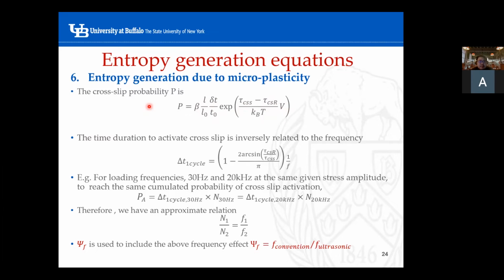So this is a probability, the cross-slip probability for screw dislocation. By this probability equation, it can be further derived to obtain the time duration to activate one cross-slip. That will be this equation.